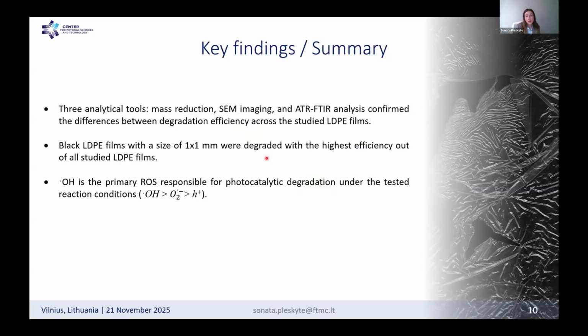So for the summary, I would like to once again mention that in this study, we checked the impact of physical properties on the photocatalytic degradation of LDPE films. And for that reason, we used 3 analytical tools: mass reduction, SEM imaging, and also FTIR analysis. And all of these 3 analytical tools confirmed that physical properties such as size and color really can make an influence and differences on photocatalytic degradation.